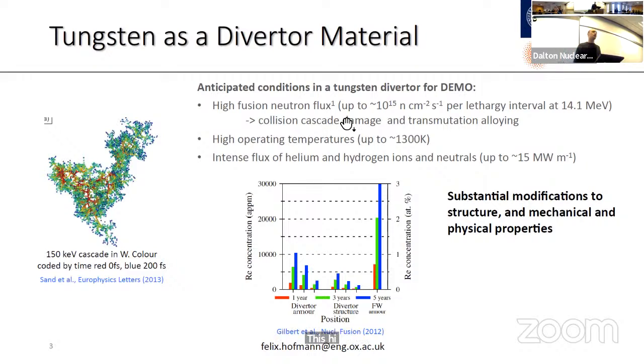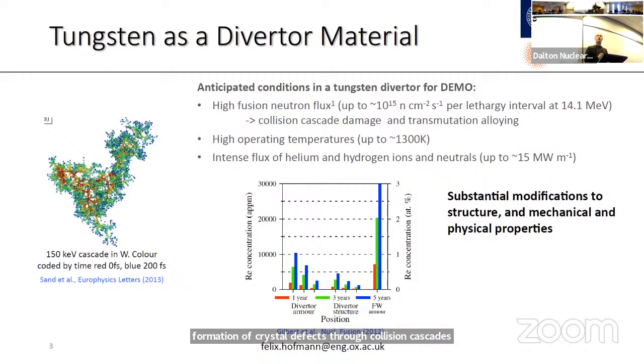This leads to two different effects. So one is the formation of crystal defects through collision cascades. The neutrons come in, displace some tungsten atoms from their lattice positions, these bounce into their neighbors, and so on, and thereby, like a billiard ball, generate this collision cascade damage. So here's an MD simulation of this from Andrea Sand.